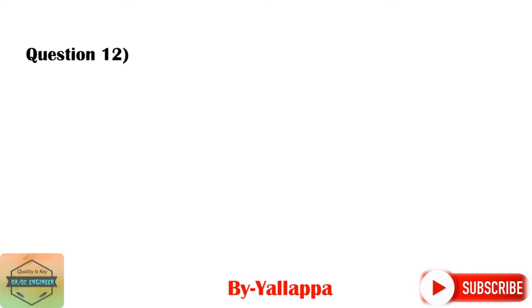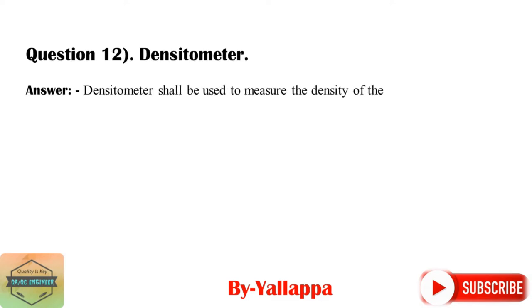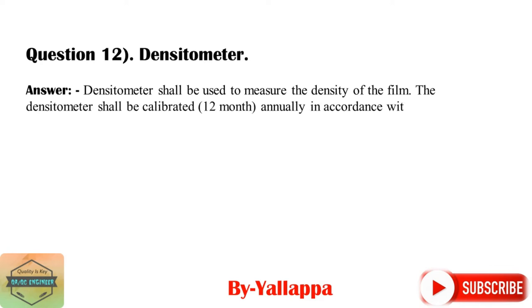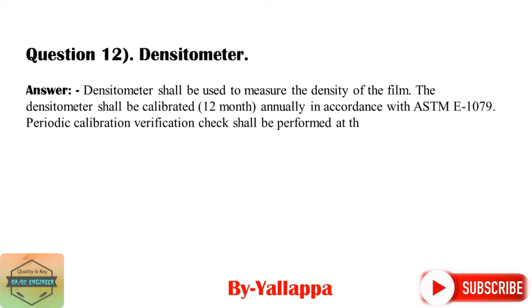Question 12. Densitometer. Answer. Densitometer shall be used to measure the density of the film. The densitometer shall be calibrated every 12 months, annually, in accordance with ASTM E1079. Periodic calibration verification check shall be performed at the beginning of each shift and after 8 hours of continuous use.